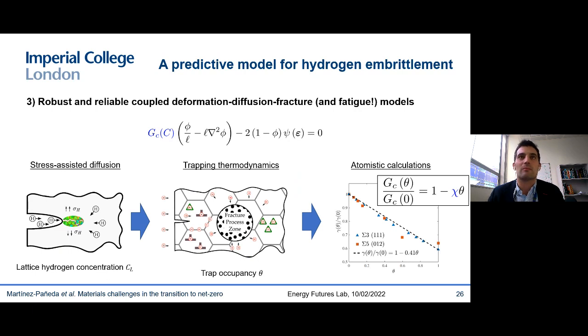I think the good news is that the framework is universal, so you could do experiments and just fit with experiments. But we could also apply the mechanistic rationale that I mentioned before, right? So we can simulate the coupling between deformation and diffusion, so we know how much hydrogen we have. We use the trapping thermodynamics to know, as a function of the hydrogen that you have in the lattice, how much hydrogen you have, for example, in your grain boundary. And then you can go to these atomistic calculations that are done offline. And for a given hydrogen content, you know how much the fracture energy is reducing. So everything can be coupled in a quantitative fashion without the need for any fitting parameters.